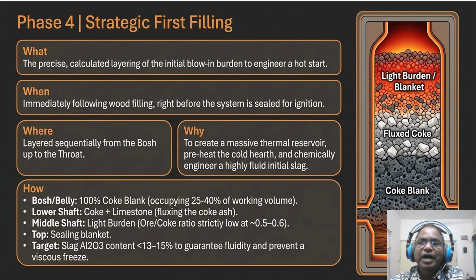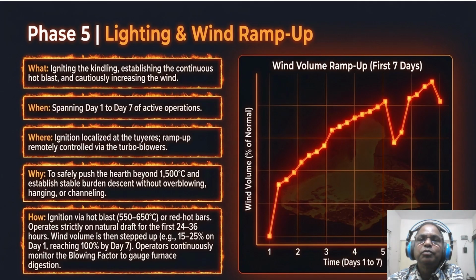The so-what factor here is the slag chemistry. We are targeting an alumina content of less than 13 to 15%. If someone asks why, it is because in the cold startup you need a highly fluid slag to prevent a viscous freeze. If your initial slag is too thick, it will not flow to the tap hole, and you will end up with a chilled hearth that could take weeks to recover. So, with the burden in place and the chemistry set, it is time for the ignition sequence, which is phase number 5.